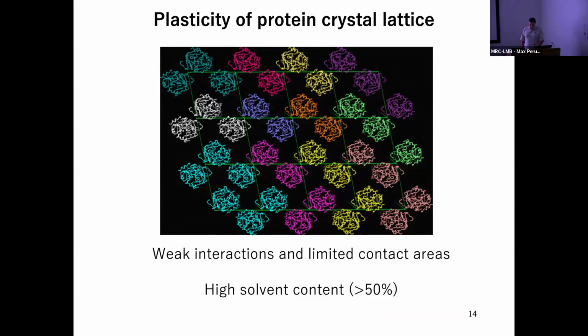The lattice of micrometer scale protein crystal is formed with hundreds of millions of unit cells. The proteins hold together through weak interactions between small hydrophobic surfaces, longer range and flexible electrostatic interactions as well, and sometimes even a single hydrogen bond. In addition, the density is typically very low, with 50% solvent content or much more. This plasticity not only limits growth, it leads to structure defects.